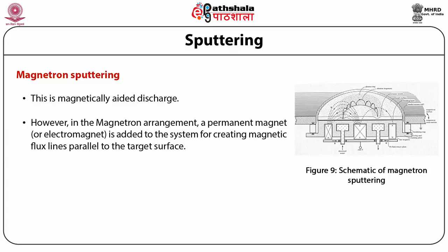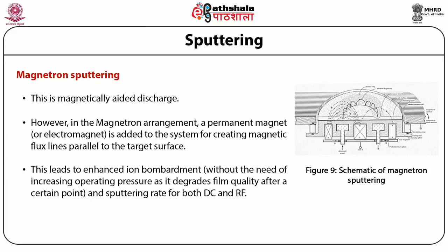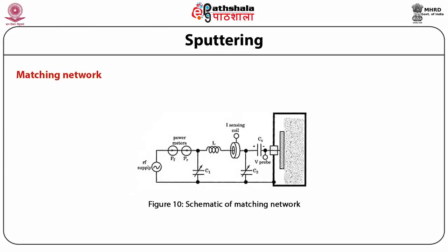This magnetic field concentrates and intensifies the plasma immediately above the target due to the trapping of electrons near the target surface. This leads to enhanced ion bombardment without the need of increasing operating pressure, as it degrades the film quality after a certain point, and enhances the sputtering rate for both DC and RF. So it uses a matching network whose schematic is shown in this figure, which is used for RF plasma coupling.